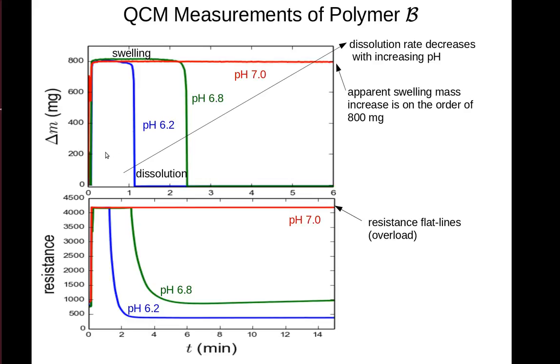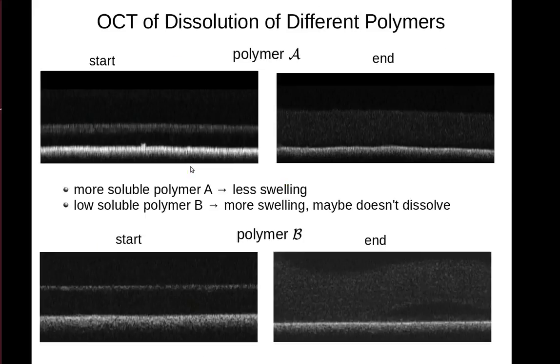The one interesting difference between this and the previous polymer is the magnitude of the swelling. The first polymer swelled on the order of tenths of a milligram, whereas these experiments suggest that there is swelling on the order of hundreds of milligrams. Also, the dissolution is very sharp compared to the more gradual dissolution seen with the other polymer. It'd be interesting to try to understand why these two polymers behave differently. For that, we can use the OCT instrument again.